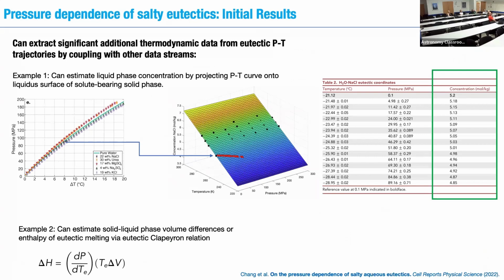One thing we can do, if we have a 2-phase liquidus surface, some understanding of the melting surface of the solute solid phase, we can actually project the eutectic PT trajectory onto the liquidus surface of the solute phase, and we can get an estimation of how the concentration then changes along this PT eutectic line. So these are now estimations of the entire P, T, X pressure temperature composition coordinates of that one-dimensional eutectic spline that exists in 3D space.